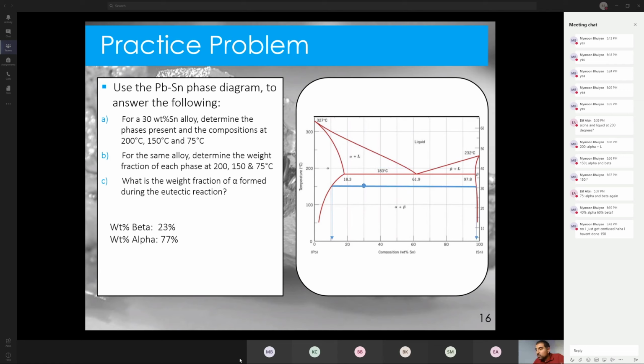That's good. And then for 150, for the alpha, we would take this distance divided by the total of the blue line. So it's 30 minus 10, divided by the total, which runs from here to here, 98 minus 10. So it's about 20 over 88. If you do the math, that's 23%. So I am taking this distance, which means I'm calculating the amount of the beta, right? Beta is here. This distance always gives you the far away phase, so the beta. So there is only 23% beta, and the amount of alpha is the rest.